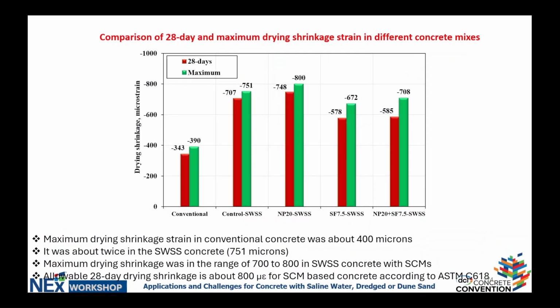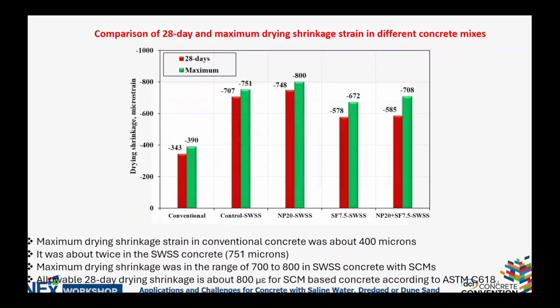If we look at the comparison of another very important property that is fundamental, particularly for flat work, especially if you are not reinforcing it, slabs on ground where it seems that this material could have a great potential, it is shrinkage. And drying shrinkage is one of the items that we need to look at. Definitely, there is more shrinkage in the case of the mixtures that we said are non-conventional with respect to the conventional one. This again is something that can be corrected with the proper use of admixtures or with a more, let's say, targeted use of the binders themselves with the substitution of some of the binders.